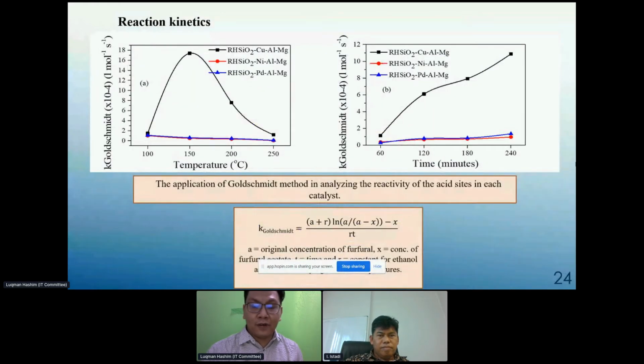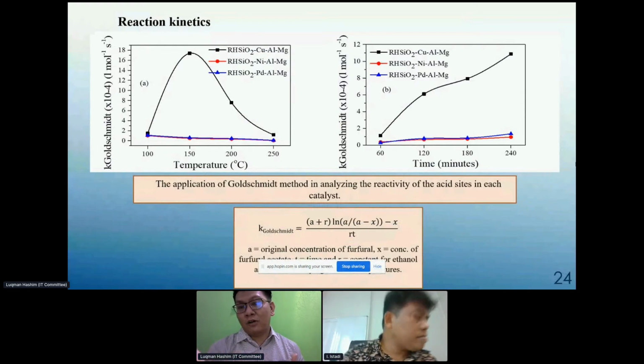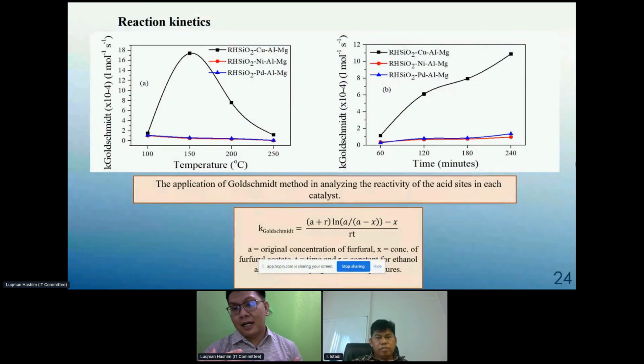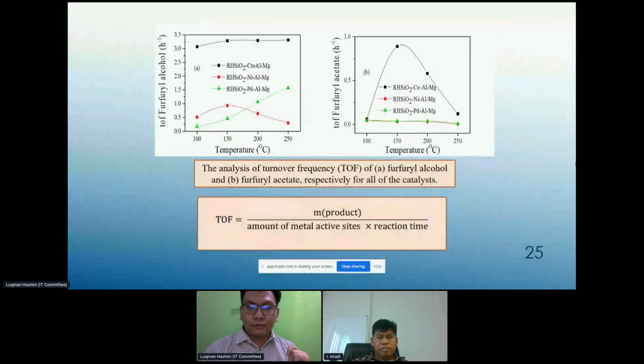So for the reaction kinetics itself, you may be wondering what the Goldschmidt method is. Basically, the Goldschmidt method is just us applying the equation down there to calculate the rate constant for the production of esterification at the acid site. And what we discovered was copper was once again great, and it produces most at 150 degrees C, and it once again outperforms nickel and palladium even when we increase the time. For TOF, we are looking at the end products, furfuryl alcohol and furfuryl acetate. Once again, copper is outperforming nickel and palladium. Nothing we can do about that for both furfuryl alcohol and furfuryl acetate. However, we can see a slight decline after the increment for nickel in the production of furfuryl alcohol. And both nickel and palladium could not outright produce furfuryl acetate, barely producing anything significant there.